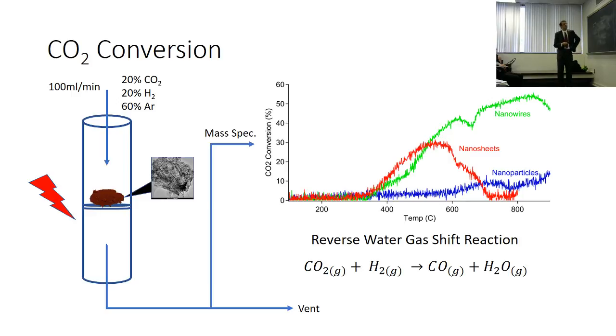So I booted up my reactor and measured the mass spec for CO2 conversion. What I found for the nanosheets and the nanowires is that they're both really good at converting CO2. The nanoparticles, not so much.